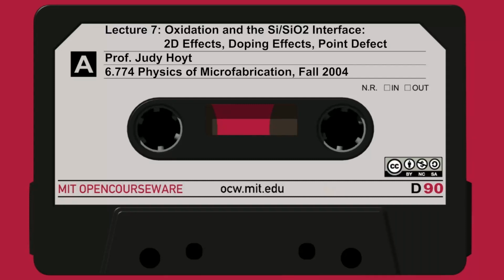As I move the Fermi level up, so I make it more and more heavily doped, I create a lot of V minus and V double minus. So I could have 100 times the number of vacancies at the surface. Oxidation needs vacancies to take place. That's the hypothesis. So people explain the enhancement of the highly doped oxidation case due to extra vacancies that are around at the surface. That's one potential explanation.